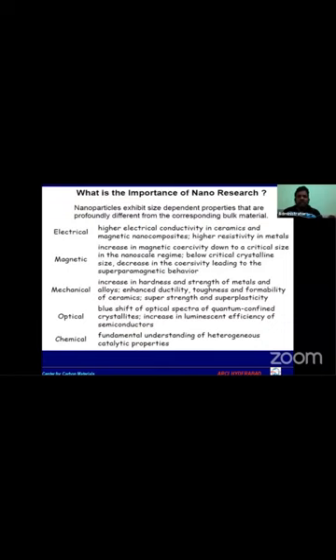Now, this is the importance of nano research. Nanoparticles exhibit size-dependent properties that are profoundly different from the corresponding bulk material. Like in bulk form, gold is yellow, but in nano form, gold is not yellow. The density of carbon is 2.26, but in nano it is 1.5. The melting point of iron is very high, 1400 plus, but it becomes 700 or something in nano. Aluminum becomes pyrophoric in nano. So the electrical, magnetic, mechanical, optical, and chemical properties are no longer the same as in the bulk form.